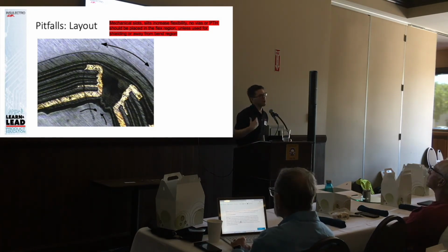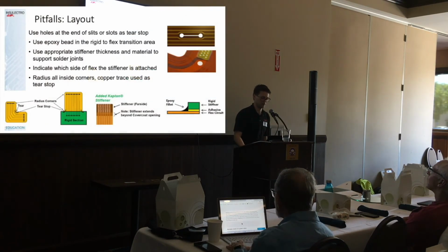And there are other problems to get to something like this. You can let processing chemistry inside the cable. It creates puffers and leakers. There's all kinds of processing problems, but ahead of time, you want to make sure you keep those drilled PTHs outside of your flex zones. And again here, this was a new designer designing their first flex board. You can see the PTHs they did drill, and some of them are a little bit too close to our keep out areas.